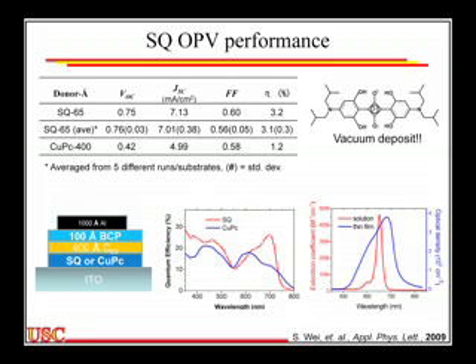Turns out, if you take 65 angstroms of that squaraine, the diisopropyl squaraine that I show here, and the reason we chose this one is it's the only one on that list that we found that actually can sublime. This decomposes when it sublimes, but you get about a 35% yield, and the decomposition product never leaves the boat. So it never goes into the devices, which is good news. But she gets an efficiency of about 3.2%.